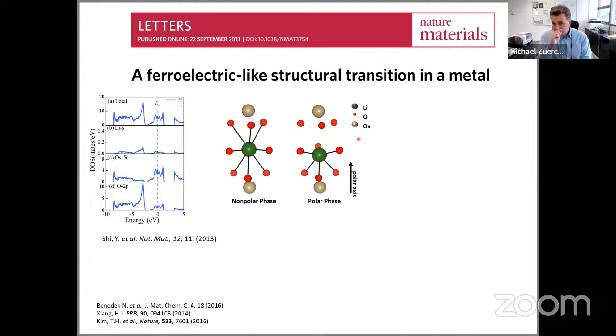Okay, so what we were now interested in doing is to start to measure this polar phase specific to lithium, because that's what we are good at with our method. The reason why this has not been studied much before with other methods is that lithium has a very low atomic number, 3, and then you have osmium, which has a very high atomic number. If you think about doing scattering experiments with electrons or X-rays in those systems, you have a problem in that the scattering cross-section scales with the square of the atomic number. So you have a very hard time seeing very lightweight lithium in these systems. Whatever you measure in a scattering experiment, aside from neutron scattering, is going to be mostly osmium, and it's hard to detect anything from the lithium.